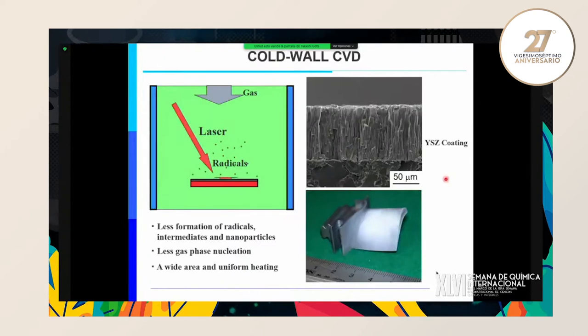But if you use cold wall CVD and heat the substrate by laser, radiation from the substrate is very small. Only the substrate is heated, and then radical intermediates and nanoparticle formation, nucleation in the gas phase, are very small. Then we can make very dense, very pure materials. The laser beam can become quite big, and the laser area to heat the substrate, about 10 to 20 millimeters in diameter, is very easy. But by using an optical lens, the laser can be expanded further.